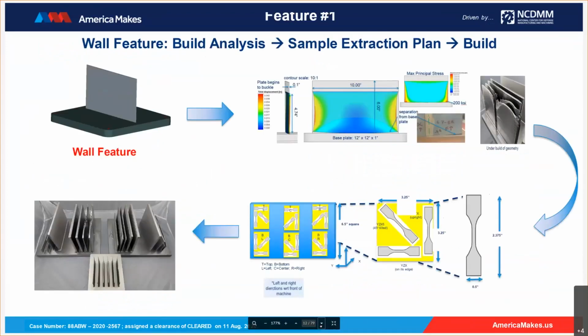So if you go to the next chart. First of all, we have to build these walls, right? So the way that we looked at it is whether the walls are buildable or feasible to build. The first thing we did was some stress analysis to see if there are warpage tendencies or crack tendencies or high stress zones that could form at different sections of the wall. So we were really cognizant of these difficulties with builds, depending on the size scale of the wall that we chose. So we down selected those based on this criteria.